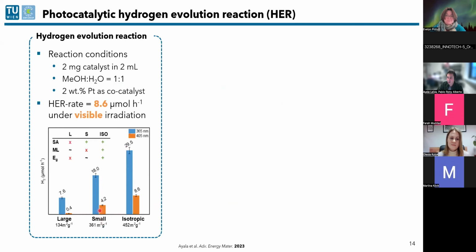So I think for this reaction, at least in my experience, the pore size is not that important. Since you have very harsh reaction conditions, an aqueous environment and UV or visible light, and usually when you have large pores in MOFs, they are also a bit more wobbly and less stable, I think they might simply not work that well because they decompose more easily. However, if you could make very large pores that are also very stable, they should be large enough so that protons can diffuse in and hydrogen can diffuse out. About the exact size, I wouldn't be sure at the moment, but I think micropores would be enough. Okay, thank you.